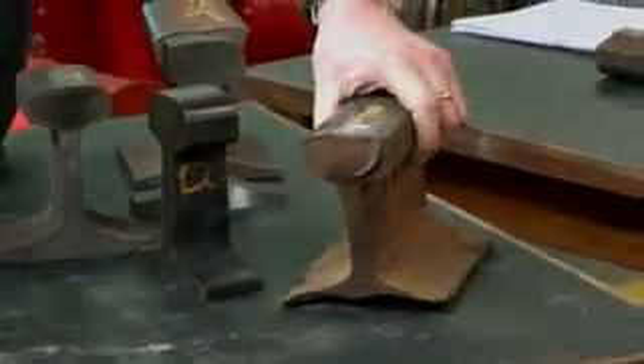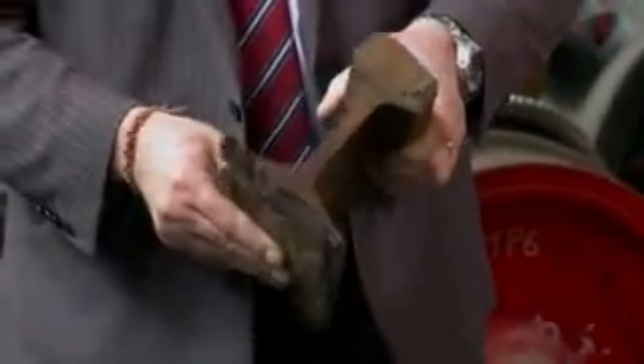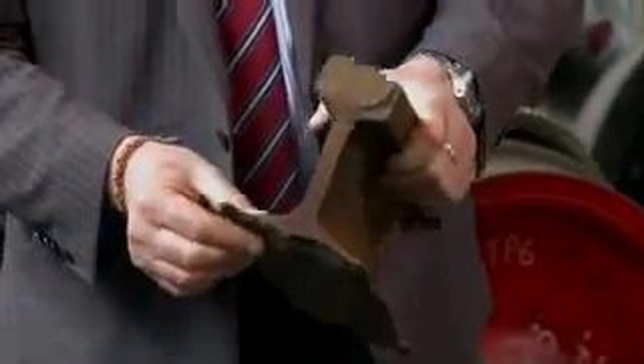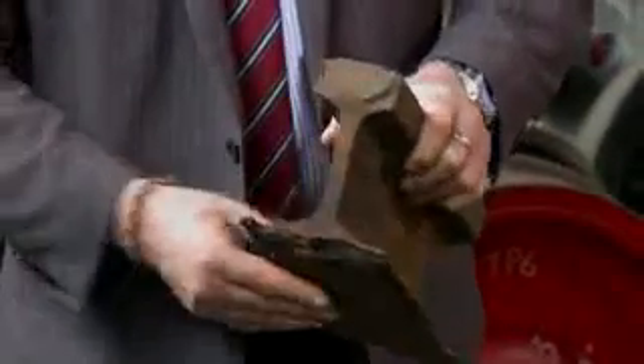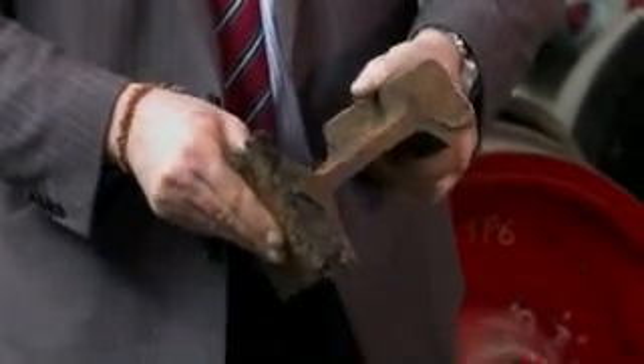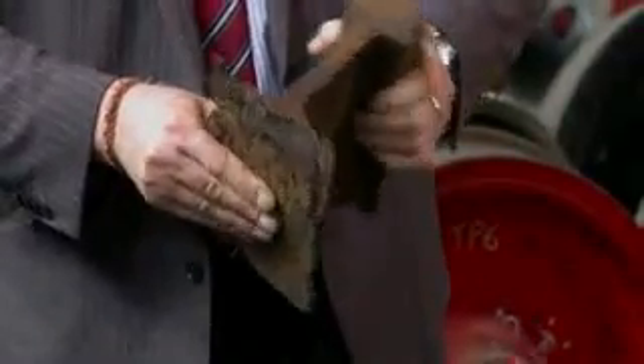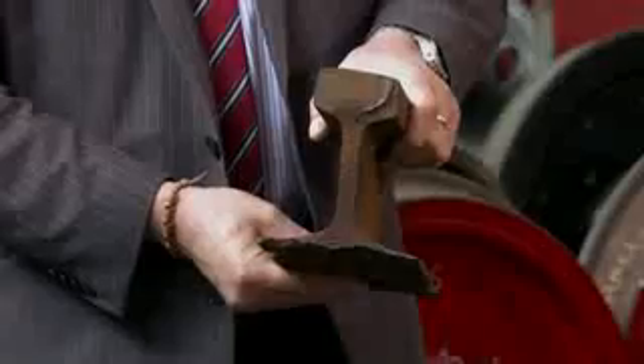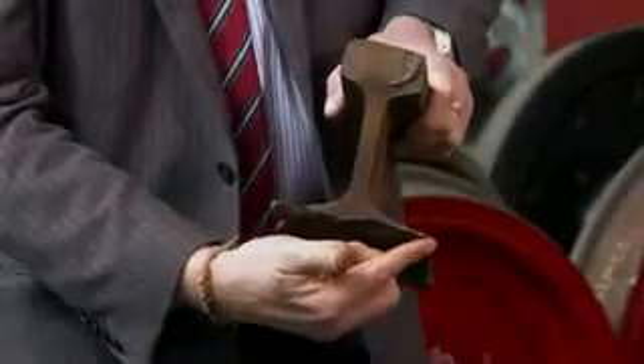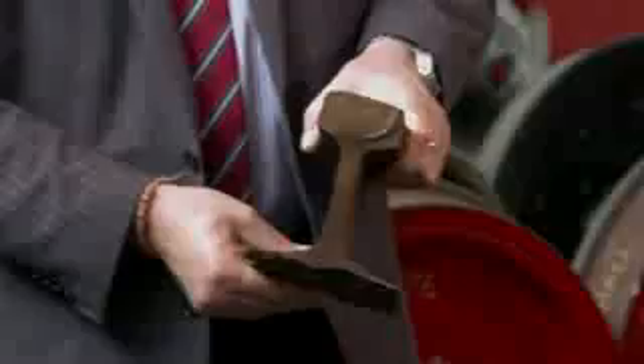Another type of degradation is corrosion. Here we have an example of a rail removed from an aggressive environment where the foot of the rail is corroded away, a large amount of material has been lost. This will result in rail failure if the rail is not removed in good time. Aggressive areas are where we would have exposure to water or perhaps the sea or salt water. Level crossings are particularly bad where we have a lot of water from the road, and also during winter salt is applied to the road which causes a significant increase in the rate of corrosion in those locations.